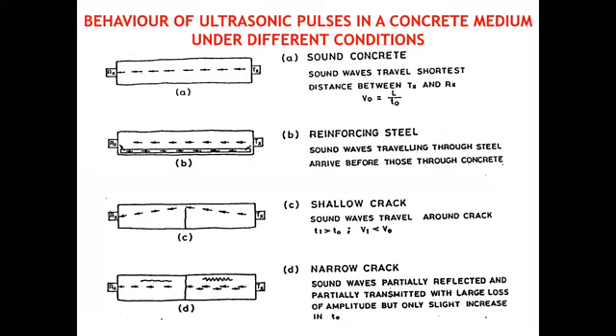If you've got voids and micro cracks, sound waves may not travel across them, and you will get an unstable reading. But if the concrete is completely saturated with water, even though it has voids and micro cracks, you will still get a higher value because you have a conductive medium, and it may not be the right value at all. So you need to check maybe once in the morning and once in the afternoon, and compare the two. If the values are not varying, then you can take it as the value.